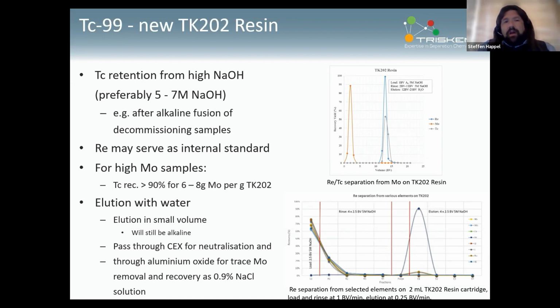And then elute with water, which is generally quite suitable, for example, for liquid scintillation counting. And you can elute in a quite small volume of water as you take away the high concentration of the cosmotropic anions. One point that's a bit particular, the water is still going to be quite alkaline, which might interfere with your measurement. So what you would want to do, and what we're looking at the moment, is just go through a cation exchange to neutralize, maybe take out last traces of cations from the solution.